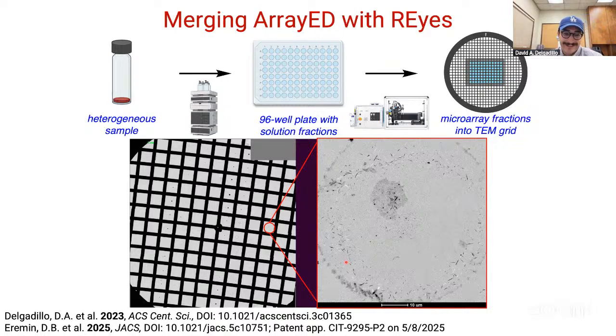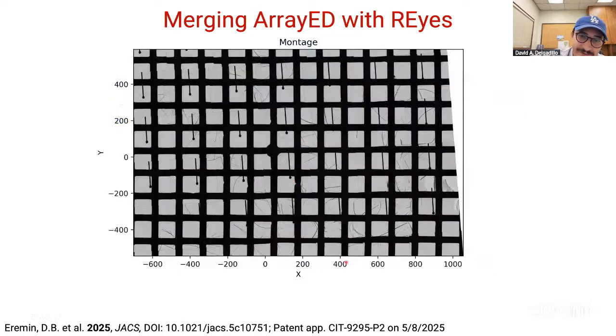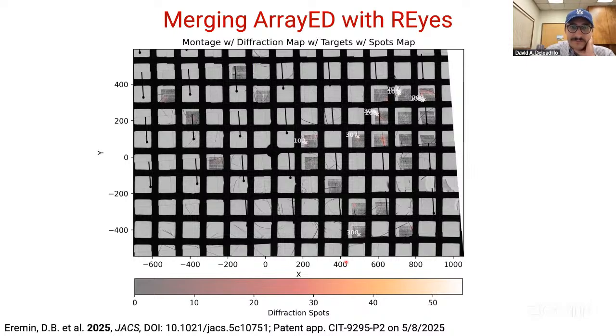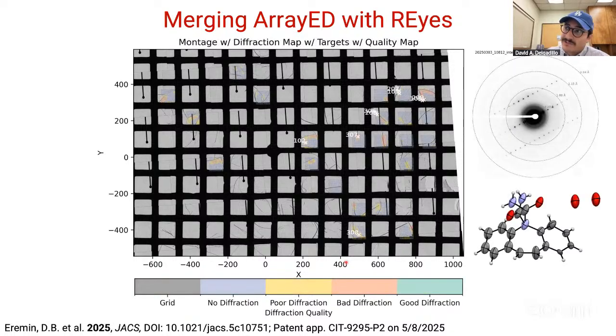So the more samples you load up in there, the longer you spend on the scope looking for something that may or may not diffract. And so the hope was, can we use Reyes from an array perspective to find regions with amenable crystallinity and diffraction. And so one of the first test cases was with carbamazepine. Although it's hard to see here, I was trying to print an R for Reyes. But these were all 10 millimolar solutions of carbamazepine printed out, and you can kind of see they crash down to thin little needles. We went ahead and montaged it, and we were able to get some nice diffraction heat maps of some regions. And then we went ahead and selected some of those targets with the highest intensity, and we're able to get a nice reconstruction of carbamazepine from an array grid.